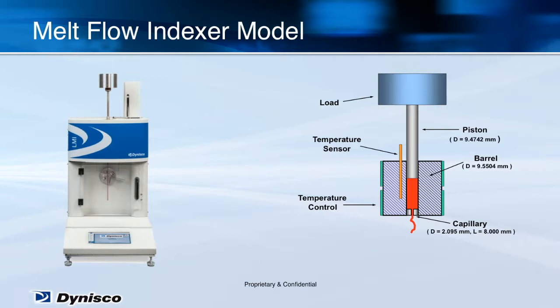In the model above, the pressure in psi would be the pounds of the test load divided by the area of the piston in square inches. The weight of the material driven out of the capillary by that pressure in 10 minutes is that material's melt flow index, or MFI. The test is a very simple and efficient way to check material viscosity.